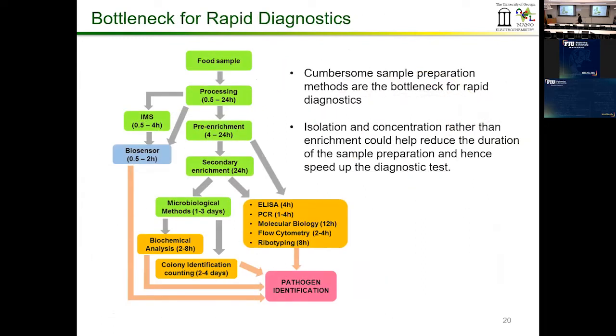Okay, so I've spoken a lot about impedance detection, which is good, but the real challenge in any rapid diagnostic tests is not the detection, the challenge is how do you prepare the sample for the detection. The real bottleneck for rapid diagnostics is the cumbersome sample preparation methods. You can see all the green things here are the sample preparation. You start processing the sample in various different ways, and there is maybe an enrichment step, and there may be a secondary enrichment, and other microbiological ones. So this could take easily 3 to 4 days if it's not a very established method.